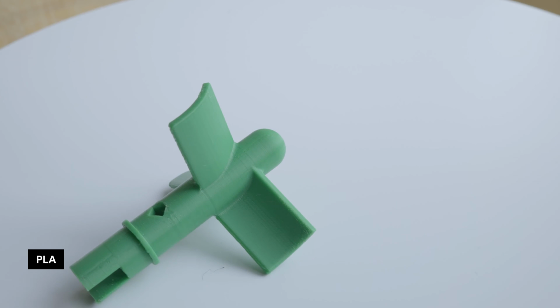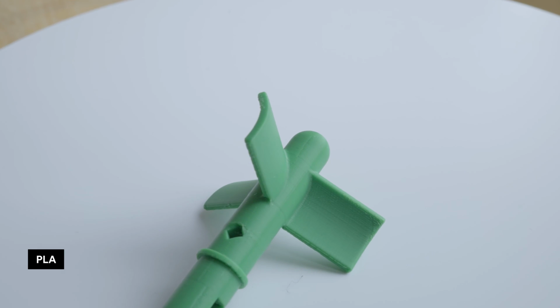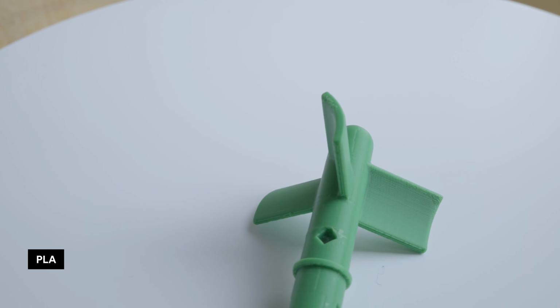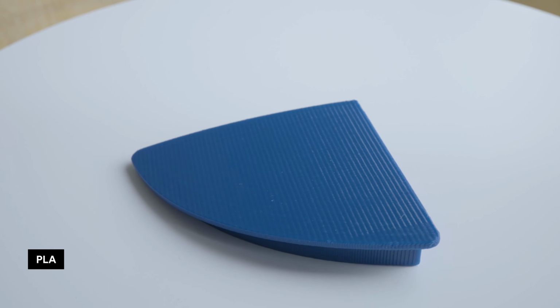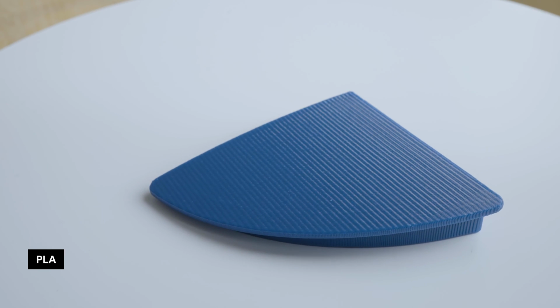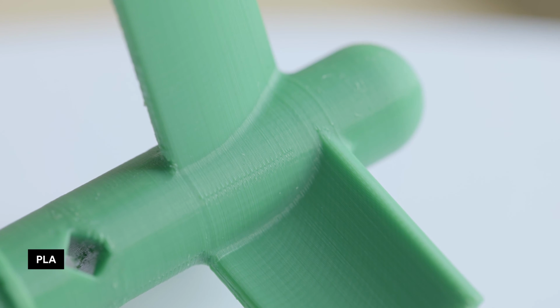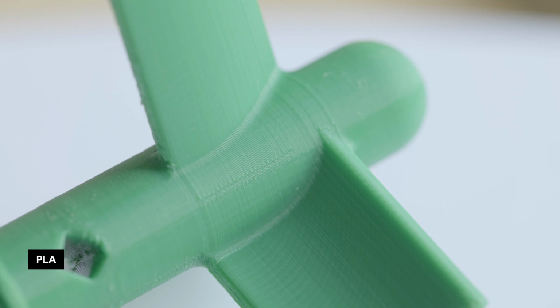Strength and durability. PLA, having a higher tensile strength, is considered stronger than ABS. However, it's important to point out a few things. For instance, PLA melts at a lower temperature than ABS. Even though there are upsides to that, this low melting point also causes the material to lose almost all of its stiffness and strength at temperatures above 50 degrees Celsius.